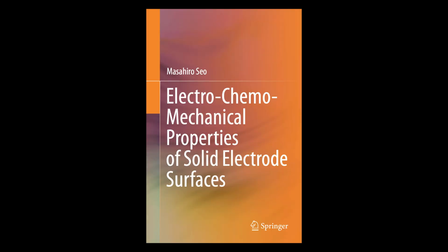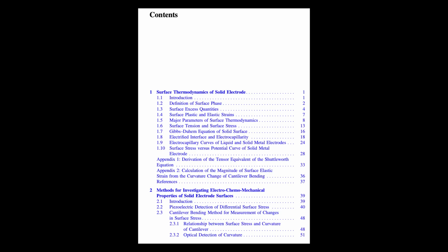Precisely. And when we compare how surface stress changes with potential to those traditional electrocapillary curves for gold, the experimental data clearly shows that surface stress and surface tension are different beasts for this solid. Okay, proof in the pudding. Exactly. And furthermore, we can define these coefficients, like the surface stress-surface charge coefficient, dς/dq, and the potential-surface elastic strain coefficient. Theoretically, these two should actually be equivalent. Two different ways of measuring the electrical effect on mechanics. Kinda, yeah. And experiments on thin gold (111) films in perchloric acid have pretty much confirmed this theoretical equivalence. They line up. Okay, so the theory holds up in practice there.